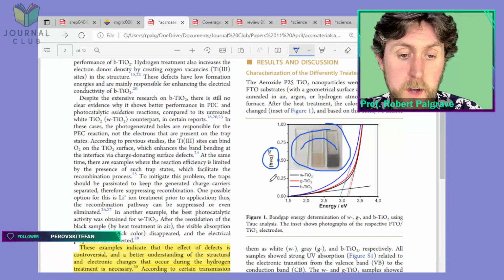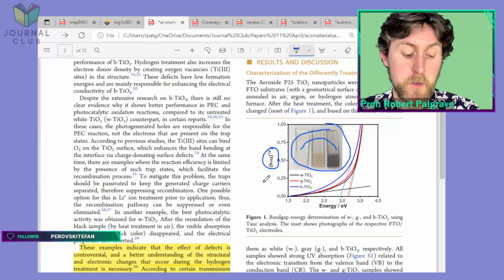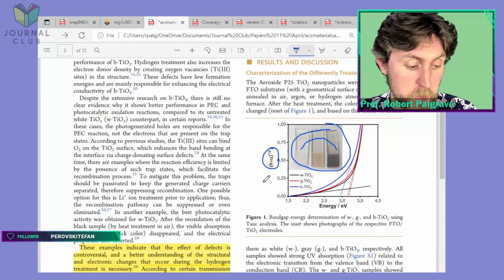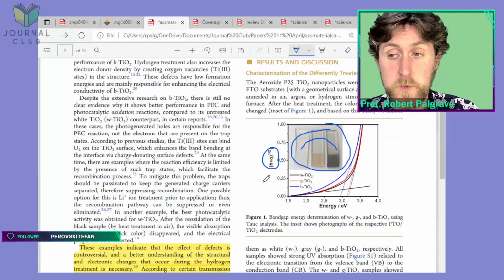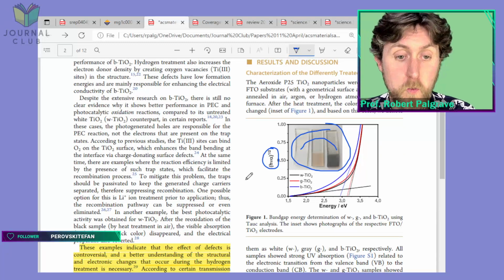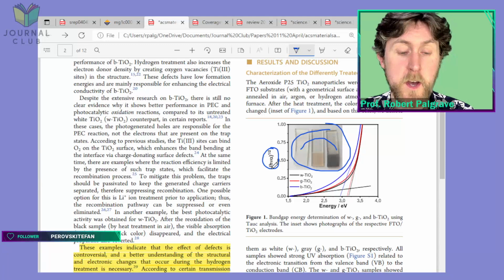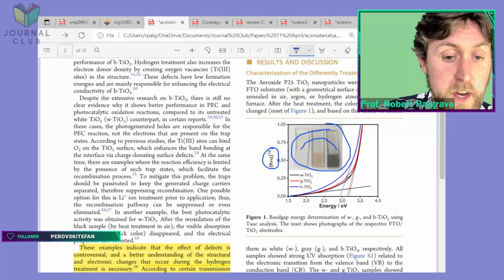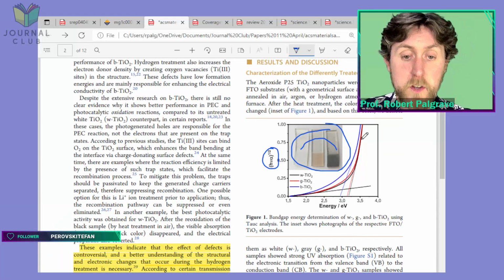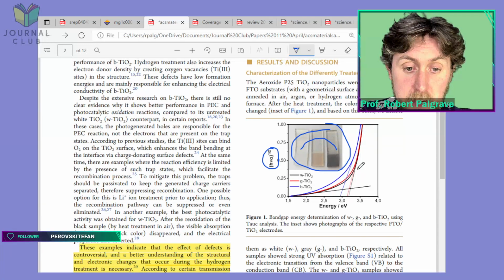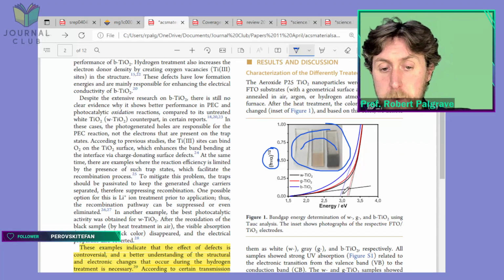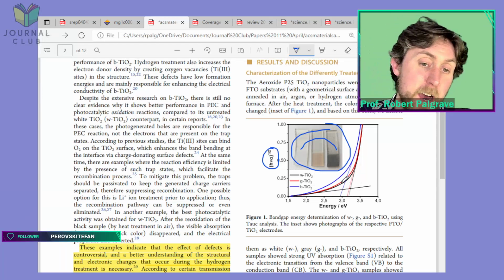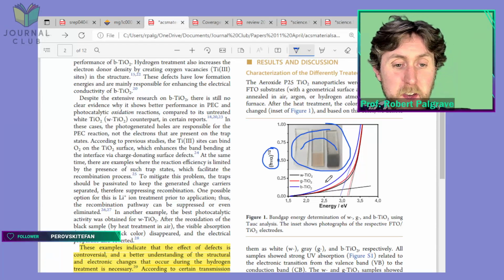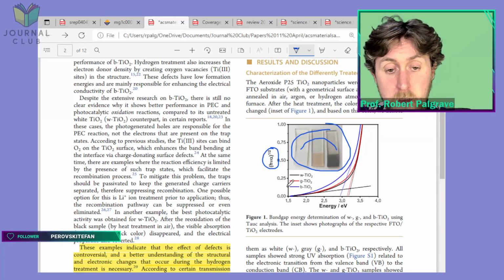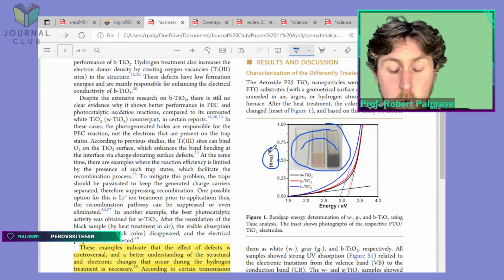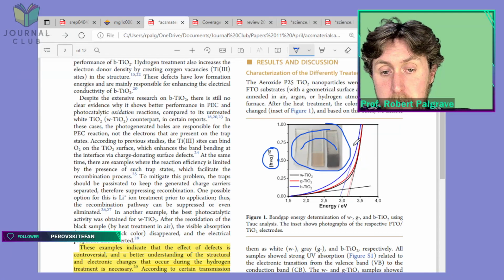So for a Tauc plot you take an absorption spectrum, a UV-visible light absorption spectrum, and you process it in a certain way, and this is one of the ways you can process it. That will give you a plot which you can extrapolate with a straight line. You can see these little dotted lines here. You extrapolate down to give you a band gap. Now, there's lots of issues with doing this. One of them is exactly how you define this straight line region.